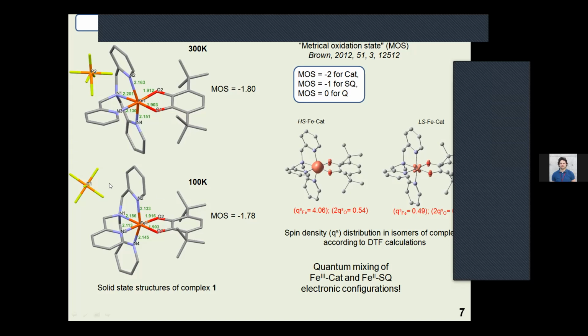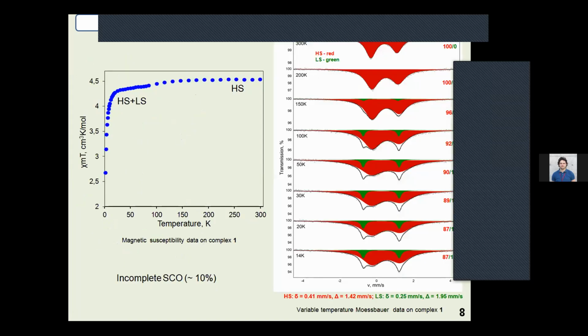Lowering of the temperature does not significantly change metal-donor atom bonds in 1. The average bond lengths are slightly shorter than those obtained at high temperature, but longer than for known low spin ferric catecholate. Such relatively small bond contraction can be explained by appearance of the low spin fraction due to incomplete spin crossover in complex 1.